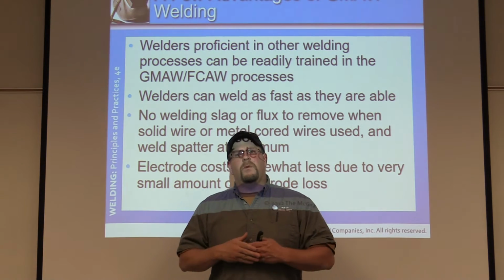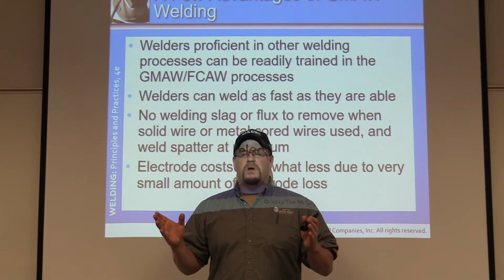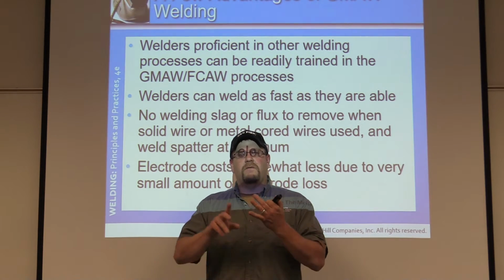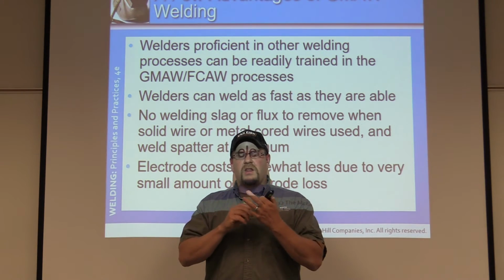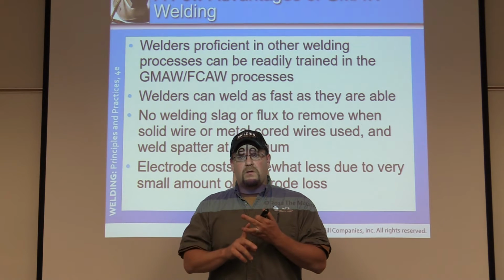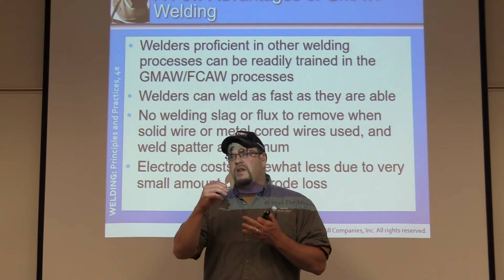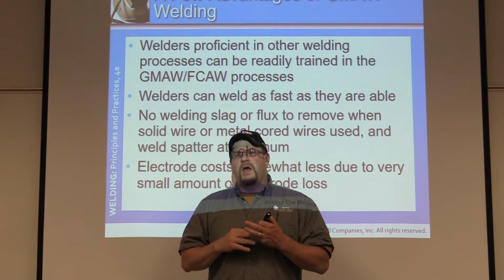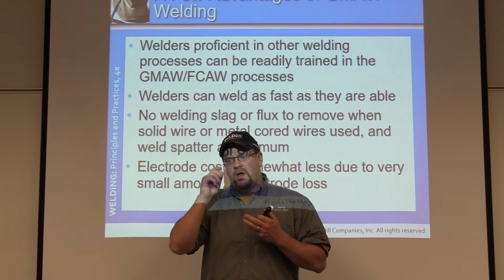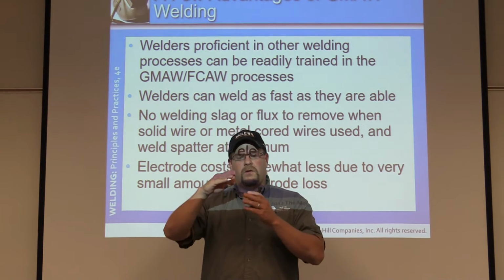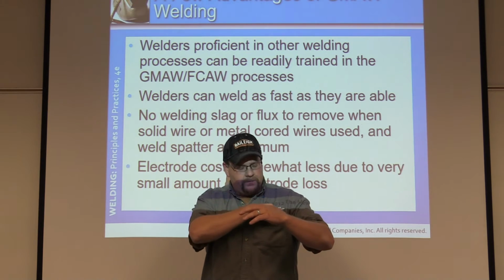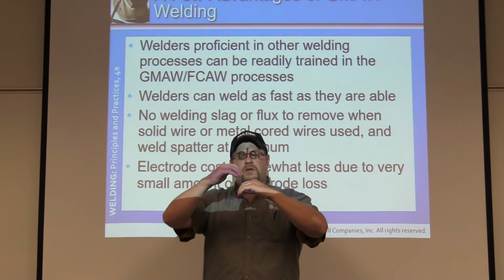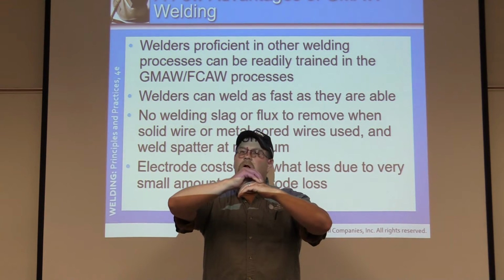They'll weld something up and we'll go to bend it and it'll completely just bust apart because they didn't clean it enough. They just thought they could weld right back over it, and they could, without grinding. You need to grind down. That top layer of metal has a little bit of silica within it. And I've seen time and time again where you lay a weld bead down like this, you put another one on top of it without grinding it,